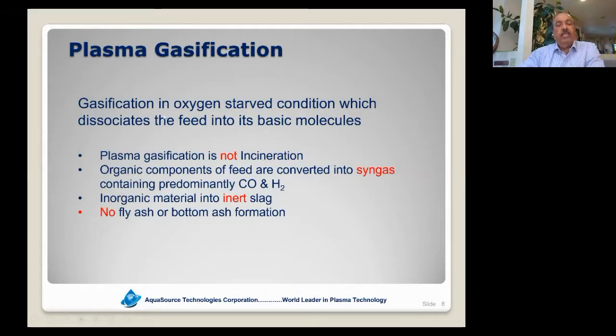Okay, so the gasification is done in an oxygen-starved condition. I want to impress on the audience that plasma gasification is not incineration. The organic components of the feeds are converted into syngas. Very key for the cement industry because you are using coal combustion, which goes through a syngas, but it's immediately combusted inside the kiln. But in plasma gasification, we have syngas that is generated, which